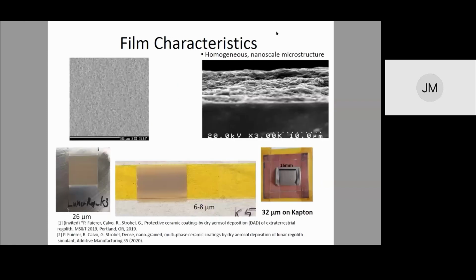A little bit about the characteristics of these films. The top left is an electron microprobe low mag image of one of the surfaces of one of our films, showing that the surface is essentially pinhole free and continuous throughout the length of the film. The top right is a SEM image of the cross-section of one of the films, showing the compactness of the films as well as the density.